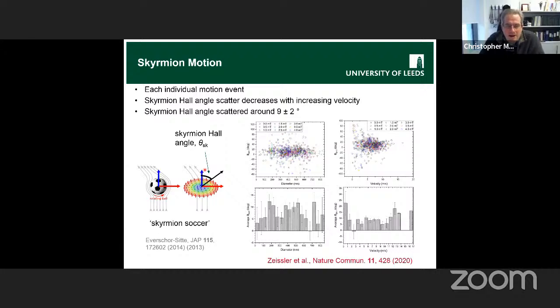So here, if we take all of our data for every skyrmion at every size, measured at every field, and just throw it onto this plot, then we can measure the skyrmion Hall angle and plot it as a function of the skyrmion diameter. And remember, the theory told us these things should be related. We don't see much relationship in this data set. It's not obvious that the angle's any different for the larger or smaller skyrmions. We've got ones here that are 700 or 800 nanometers across, a few here that are 100 or less, mostly in the middle, like 300, 400, 500. So the average angle is around 9 degrees. This cloud of data points is slightly above 0, but there's no obvious dependence on diameter.